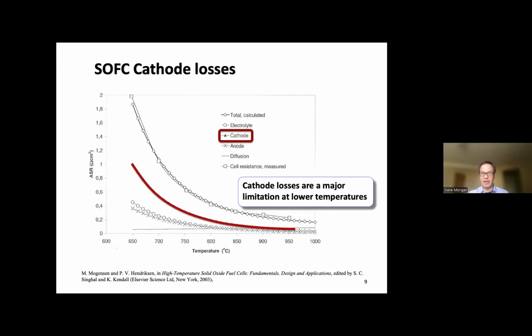And what happens is, as you cool down your system, the total resistance goes up quite dramatically. Essentially, there's an exponential increase. And that's due to all kinds of processes that get more and more difficult to run at lower temperature. The one we're focused on is the cathode, which I'll say more about in a minute. The cathode essentially pulls in the oxygen and splits it. And that chemical reaction is actually fairly difficult to catalyze.